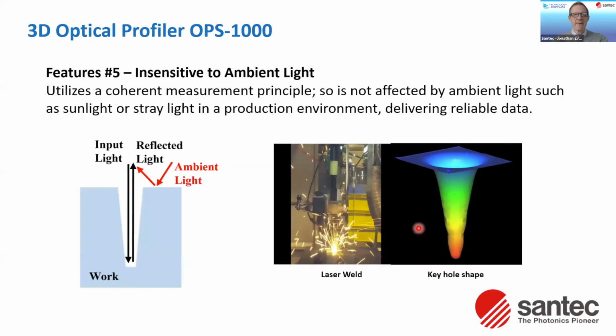And the final feature is the insensitivity to ambient light. So it's a coherent technique. Stray light, sunlight, other sources of light that are incoherent with our measurement signal will not be detected and don't interfere with the measurement. Taking a fairly extreme example, here's a welding system in the presence of a multi-kilowatt laser, but we can still get this nice profile of the keyhole shape, even under those conditions.